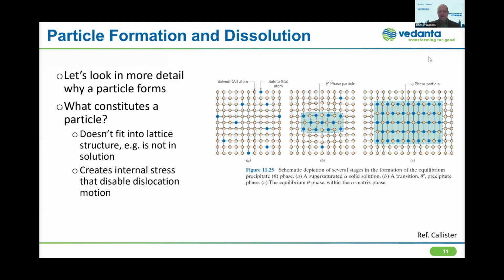So looking at this, this is the crystal lattice we spoke of. This particular example is calling out copper atoms, so it's for a 2000 alloy, but it's exactly analogous to what we're talking about, where we have the solvent. It's primarily aluminum in this lattice, and our alloying elements are mixed within, and from a distance, they're indistinguishable, and everything fits. A particle, on the other hand, is something that is distinct and different. It is not in solution, but it is a distinct component. So in this example it's copper atoms; for us, it would be magnesium and silicon for 6000.